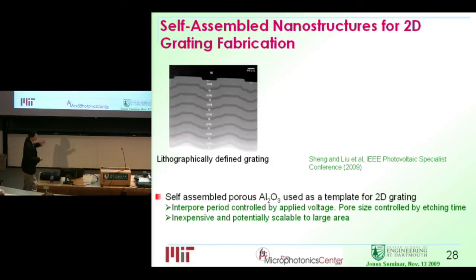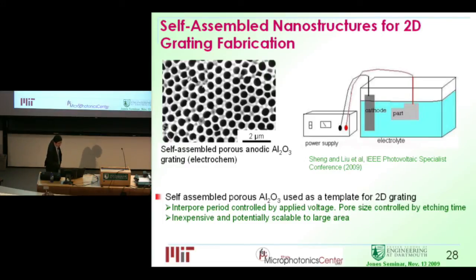And for the grating fabrication, we used to do complicated lithography to demonstrate the concept, but recently we're moving on to doing self-assembled structures. Many of you may be very familiar with this anodic aluminum oxide, which you can do with electrochemistry. You can control the pore size by the pore period, actually the interpore distance, by the applied bias. And once you have this period, you can enlarge the pores to the extent you want by further chemical etching.